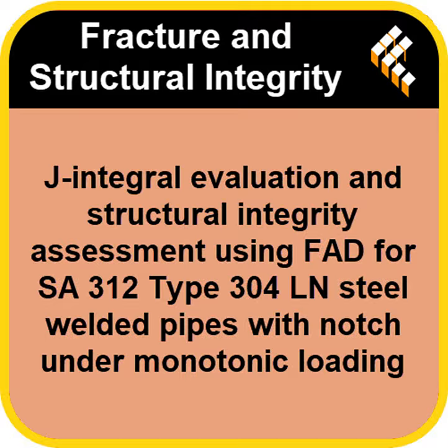So if your LR is, say, a 0.5, you're using half the plastic capacity. And if it hits 1.0, you are theoretically right at the point of collapse, regardless of any crack. Precisely. A higher LR means you are closer to that plastic failure point. Now, for the other axis, KR. Okay. Well, this is the fracture ratio and measures the component's resistance to fracture. Okay, so if I picture LR as the maximum strength test, maybe KR is more like the sharp object test,